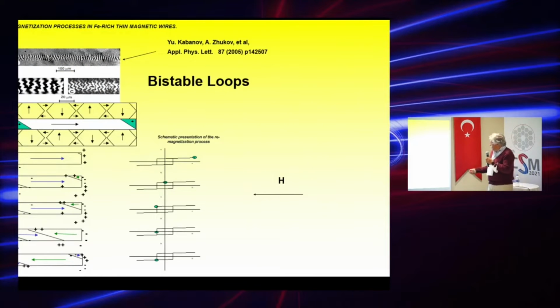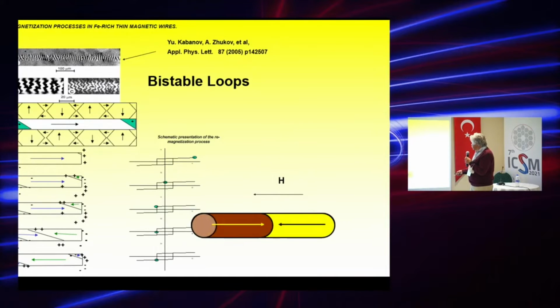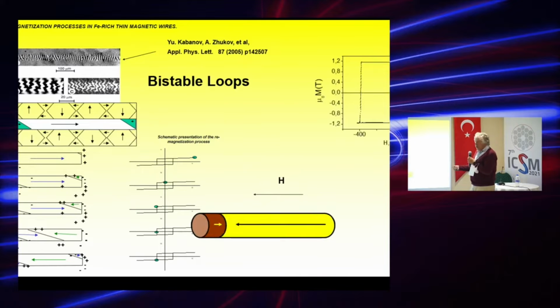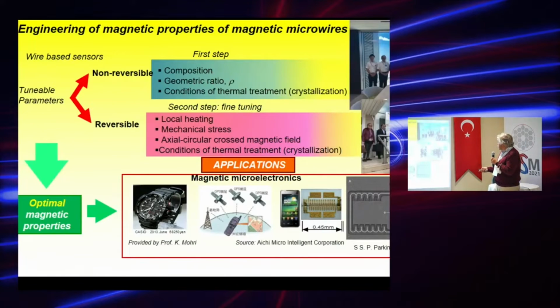In fact, iron-rich materials present this kind of domain structure with a single domain responsible for this fast domain wall propagation. Once we change the external magnetic field from, let's say, positive to negative, at some point we create the domain wall, which propagates very fast through the material, and then we have that perfectly square hysteresis loop. This is a real loop, and as you can see, it is almost perfectly square. This shape is responsible for the very fast domain wall propagation.